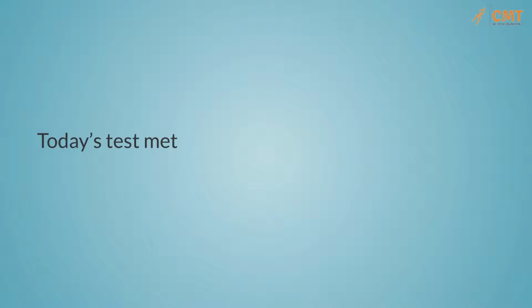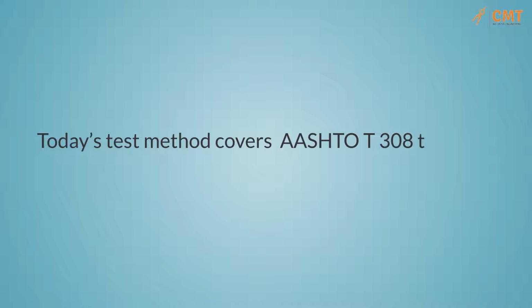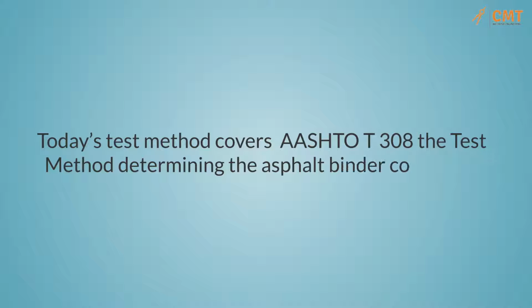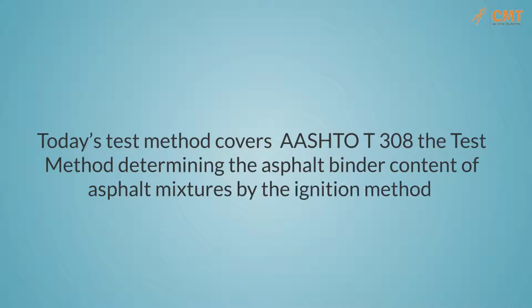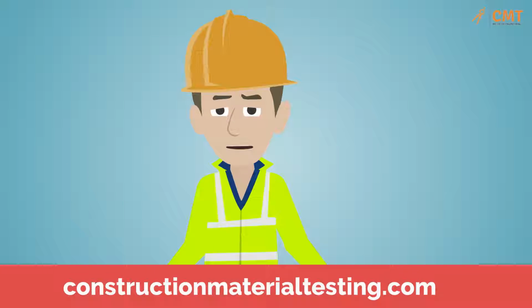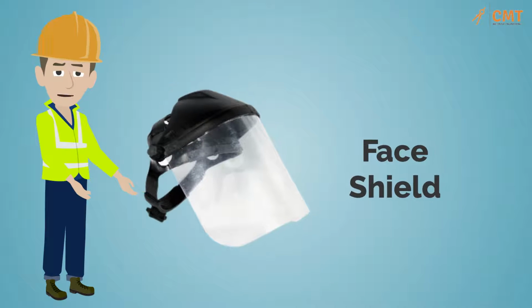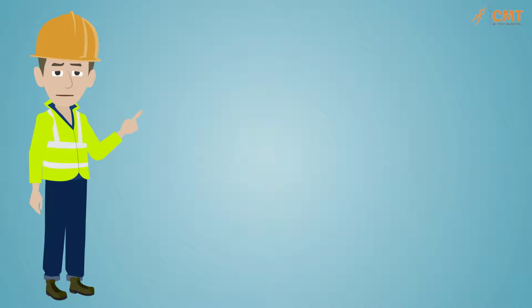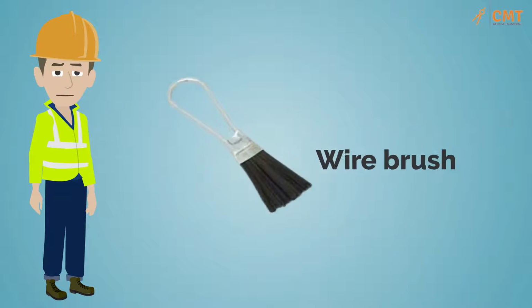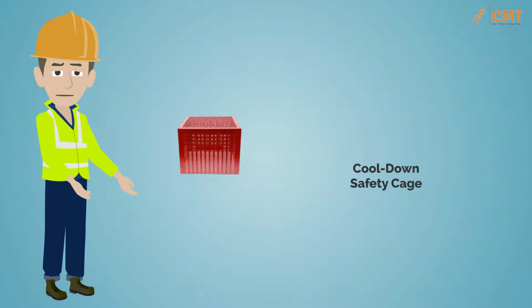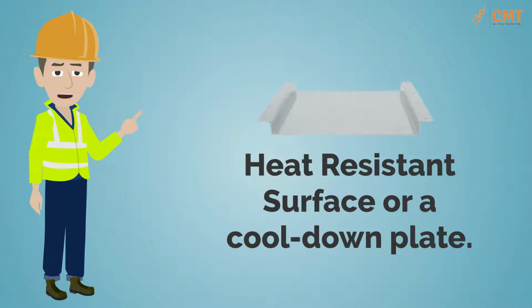Today's test method covers AASHTO T308, the test method determining the asphalt binder content of asphalt mixtures by the ignition method. The tools you need for this test are the ignition oven, face shield, heat-resistant gloves, loading fork, scale, wire brush or asphalt tool, cool-down safety cage, and a heat-resistant surface or a cool-down plate.